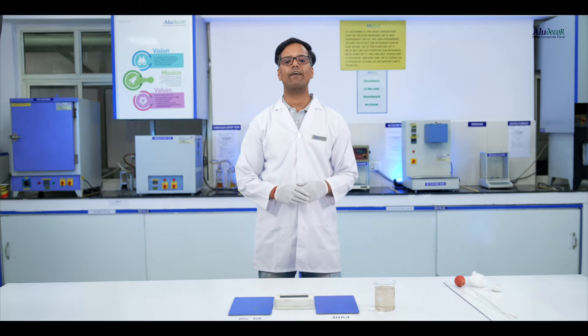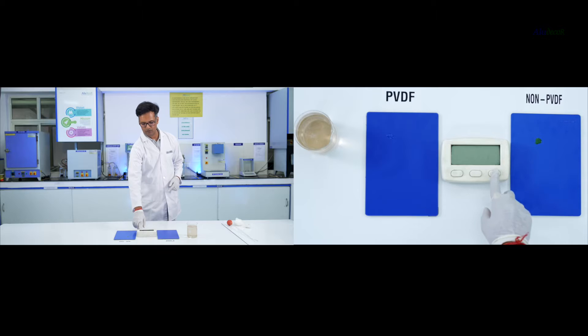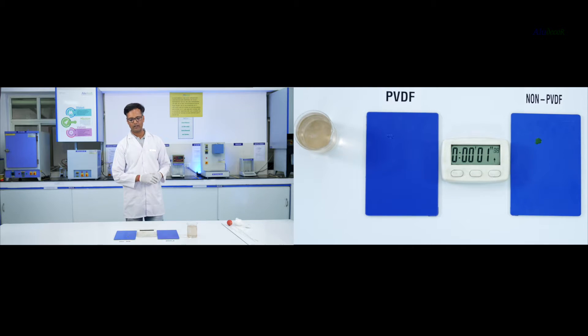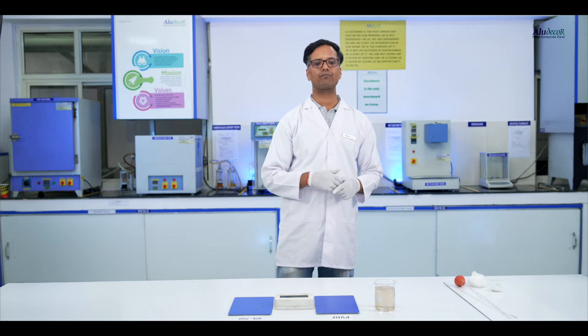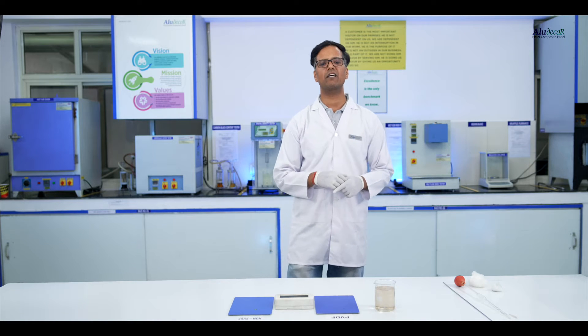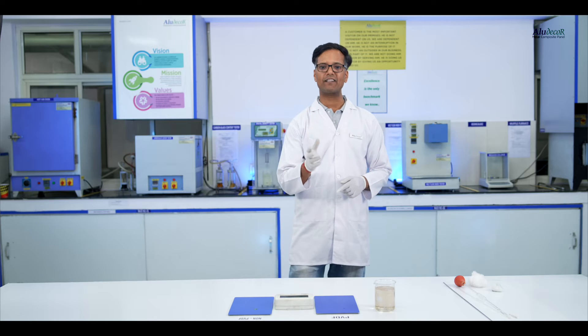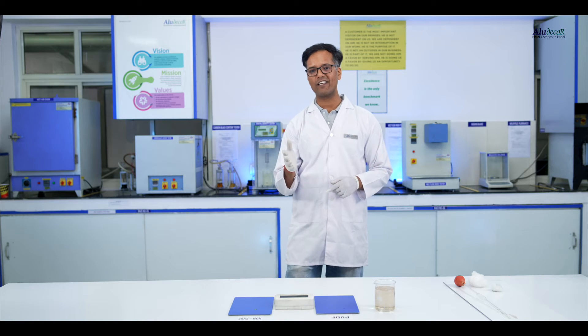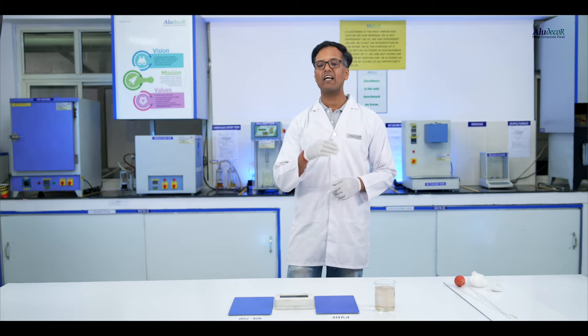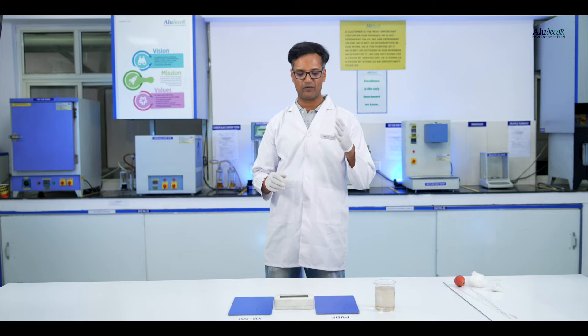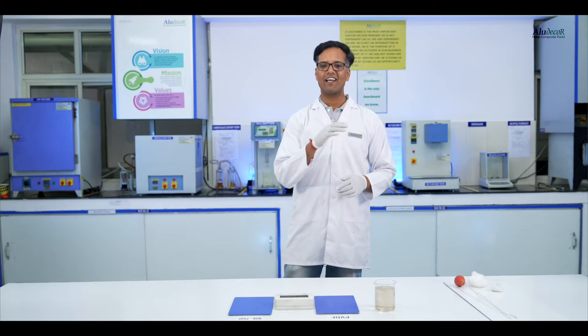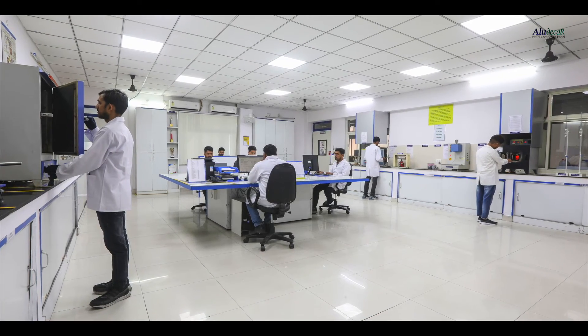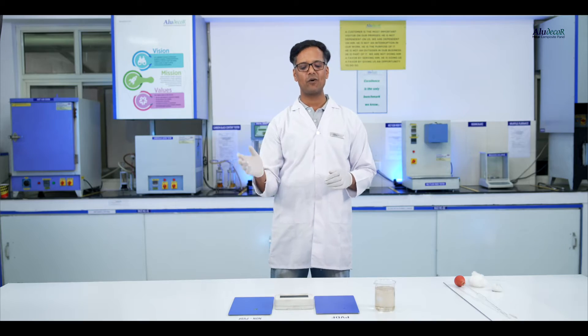Now we wait for two minutes. In the meantime, we would like to inform you this test is done based on the test method for effect of household chemicals on clear and pigmented organic finishes such as PVDF, non-PVDF, and other finishes in accordance with ASTM D 1308.